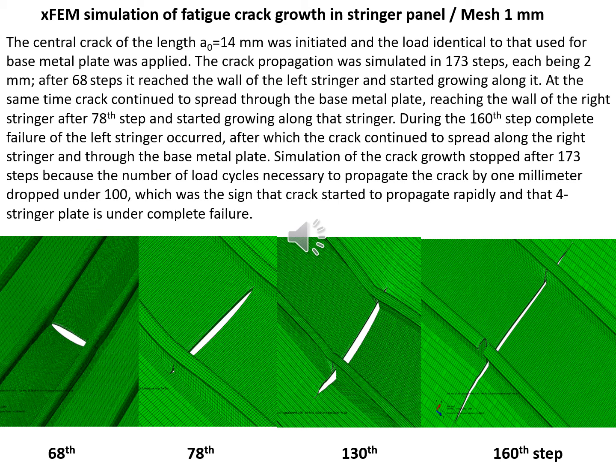After 78 step, stringers are partly cracked. After 130th step, crack is definitely going along the base metal, and then still along the stringers, and finally after 160th step the whole stringer, at least left one, is cracked or broken. So this is quite interesting and not completely in accordance with experimental observations, which are not shown here, which indicate that stringers actually do not break before the whole plate breaks.